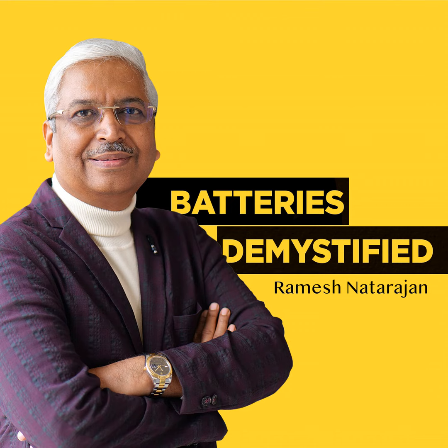The cadmium electrode resembles a cylindrical pencil with a diameter of roughly 10 mm. Typically, the length used ranges from 10 to 15 centimeters. Before usage, it is necessary to immerse the electrode in sulfuric acid with a specific gravity that matches the specific gravity of the battery for a duration of 1 to 2 days. After the cadmium rod is prepared, it can be securely attached to a brass holder. This holder is designed to facilitate the measurement of both the overall cell voltage and the voltage of the cadmium electrode with respect to that particular set of plates.